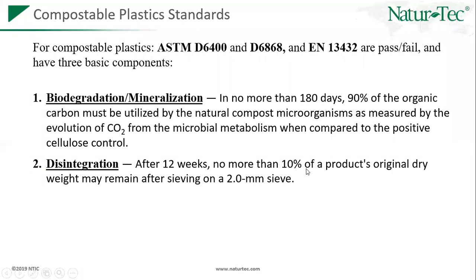The reason they put this is, let us say you take something like aluminum foil. Aluminum foil contains no carbon, which means you would meet the mineralization methodology, because the mineralization, this first step, is only for the carbon content in the material. But the reason they also put in the disintegration is to check whether the material gets assimilated into a form which is indistinguishable, or does it keep lying out in patches? This is what the disintegration test does.